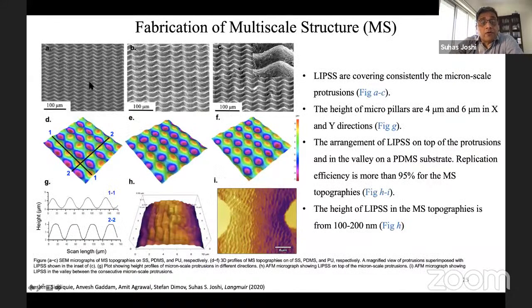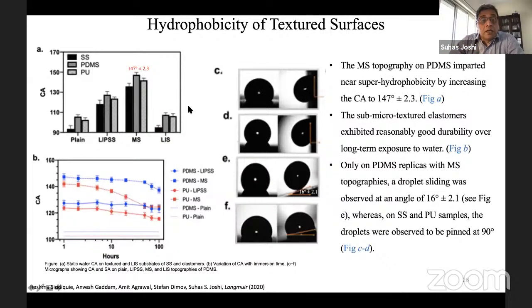So here it gives some more idea about the periodic structures, but these are not only periodic structures. On top of the periodic structures, you find that there are multi-scale features: microscale structures at the bottom and nanoscale structures on top of them. So these are superimposed, one structure over another structure. This is again possible by means of scanning strategies, that is line and pulse overlaps, and then multiple scanning on the same surfaces by the laser, modulating the energies and modulating the pulse intensities, and so you can create the multi-scale structures. You will find that these multi-scale structures have much superior properties compared to the other surfaces.